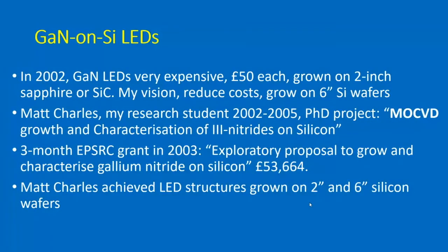And then there are what are called edge effects around the edge of the wafer where the LEDs don't work so well. Actually the edge effects are less on one 6-inch wafer than on 9 2-inch wafers, and so you get about 10 times as many devices. And it's as cheap to process a 6-inch wafer as a 2-inch wafer, so the size of the wafers brings down the cost as well. And I had a research student. I gave him this project in 2002, to try and grow gallium nitride devices on silicon, and we got a quick grant and everything.